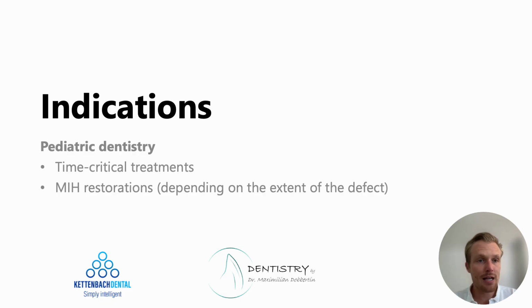MIH, so molar incisor hypomineralization restorations, also can be restored with bulk fill composites, especially in the posterior region. There we have to be sure that the retention profile on the tooth, so the microstructure, is good enough. So we need a good preparation or combining this with aluminum oxide sandblasting, so air abrasion, and then a good etching and adhesive protocol, obviously.